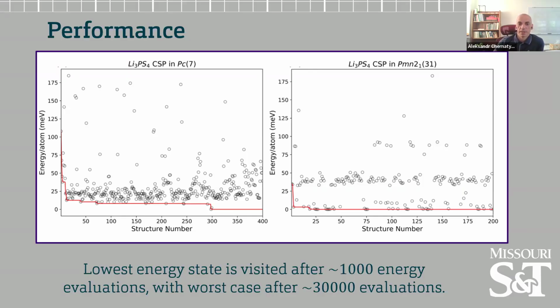that the numbers here indicate really the count of the local optimizations. By the time we got to the 20th local optimization or so, which means that we considered about 1,000 energy evaluations, we already found the lowest energy structure. So again, something which has a relatively low degree of dimensionality. This is how fast you're going to find it.